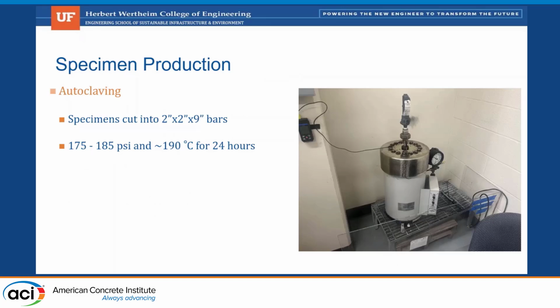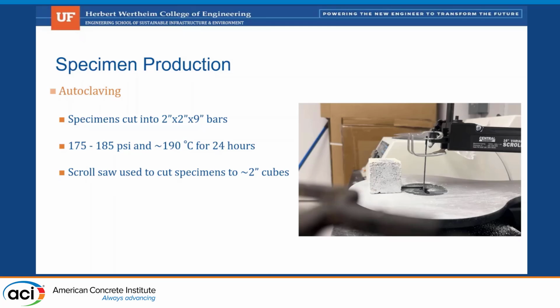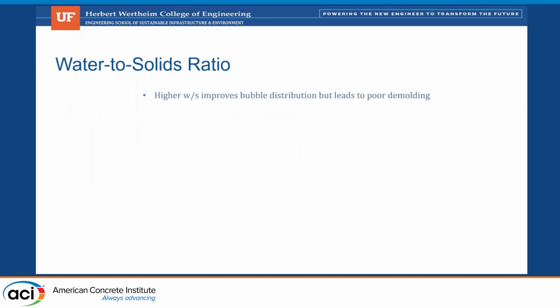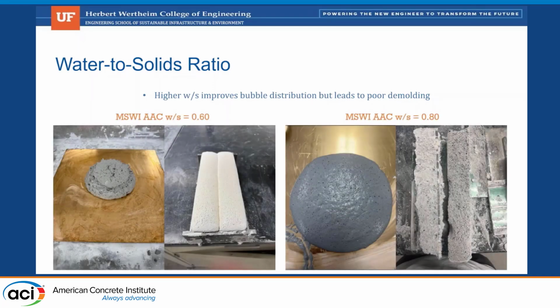That's our autoclave. We put those 2 inch by 2 inch by 9 inch bars into the autoclave, let it go at 190 for 24 hours, and then we can scroll saw these and cut them into whatever sizes we want. What we did learn is that a higher water to solids ratio improves bubble dispersion, which is kind of obvious. The more workability you have, the better the air dispersion, or in this case, hydrogen dispersion.